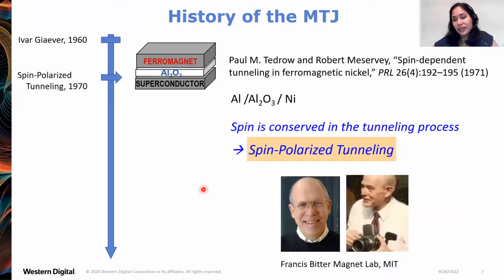Then a few years later at the Francis Bitter Magnet Lab at MIT, Paul Tedrow and Robert Meservey were also using aluminum electrodes and aluminum oxide tunnel barriers, but this time the aluminum was a superconductor. And they had the idea of using a ferromagnet, nickel, as the counter electrode. And what's special about ferromagnets is that you have this asymmetry of the density of states according to spin. And so with this tri-layer tunnel junction, they showed the asymmetry of spins tunneling from the Fermi level of the nickel into the aluminum superconductor.